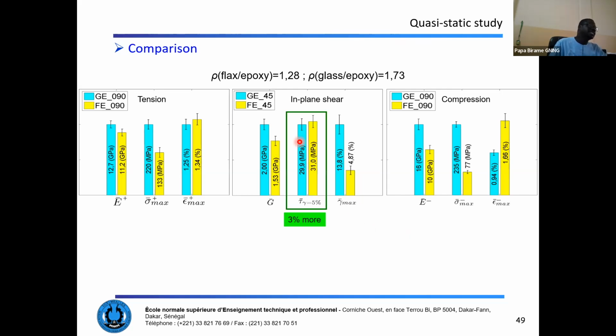divided by the density to compare the specific properties. The smaller density of the Flax epoxy composite, which is 1.28, compared to the glass epoxy composite, which is 1.73, diminishes the difference between the results we had of glass epoxy compared to Flax epoxy. But it appears overall that glass composite has better properties than Flax epoxy composites.